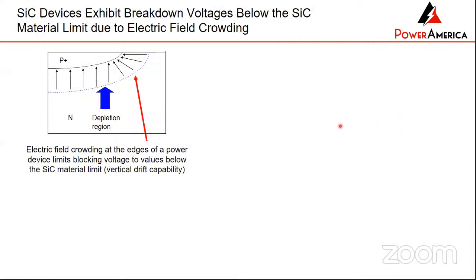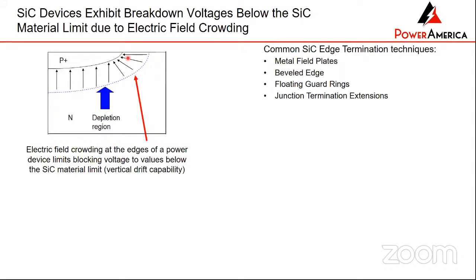So another thing we need to take into consideration when it comes to power devices is the electric field buildup. This is a PN diode, and you can see at the corner of the device, the electric field becomes very strong. It becomes dominant. So the idea is that you have a high breakdown voltage here, theoretically, based on the thickness of this layer, but you're not going to get to that voltage because you got breakdown at the corner of the device at the surface.